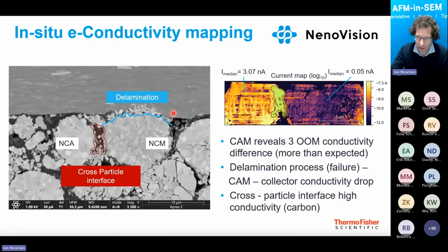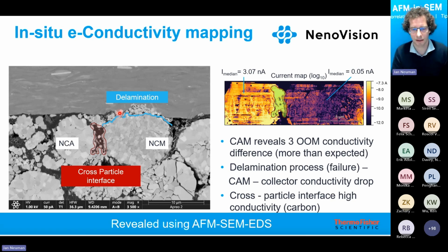And by the end, in the third part, we can have a look and analyze the conductivity of the cross particles on the cross section. In this case, it's carbon, so we see it's heavily conductive. So from this one analysis, it can be used for 3 different studies. Now you can imagine that you have different materials, different compositions after different stages of cycling, etc. All of that you can reveal using AFM, SEM, and EDS together.